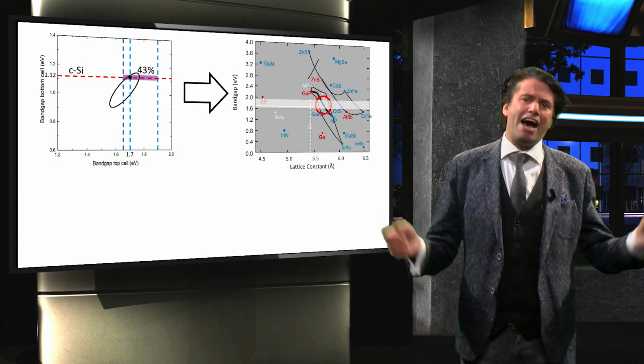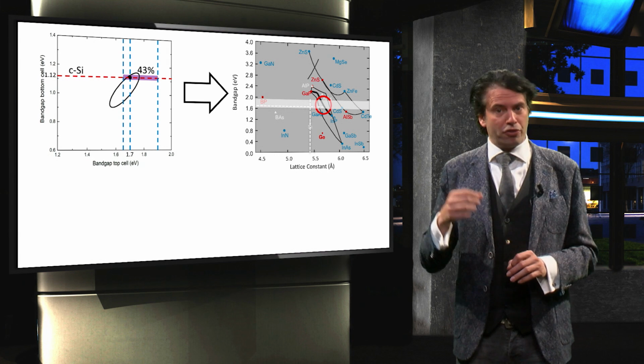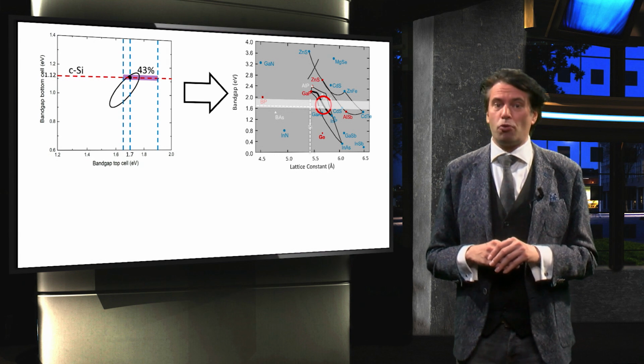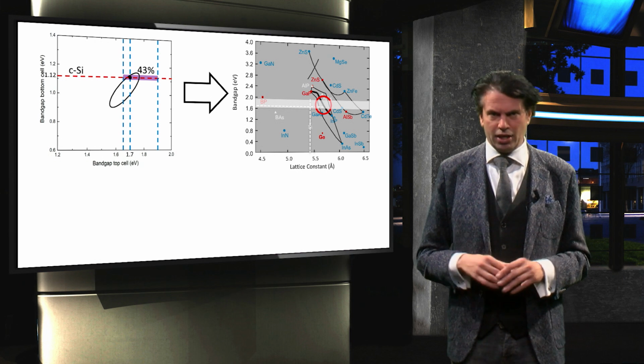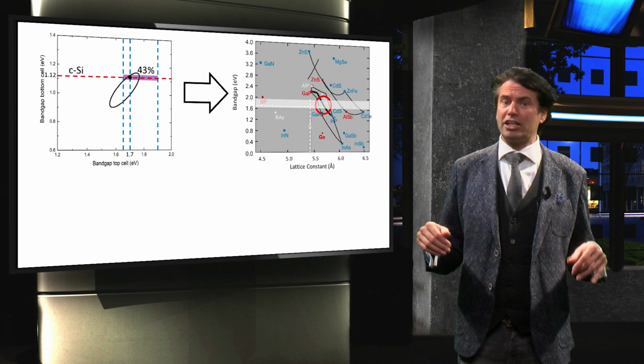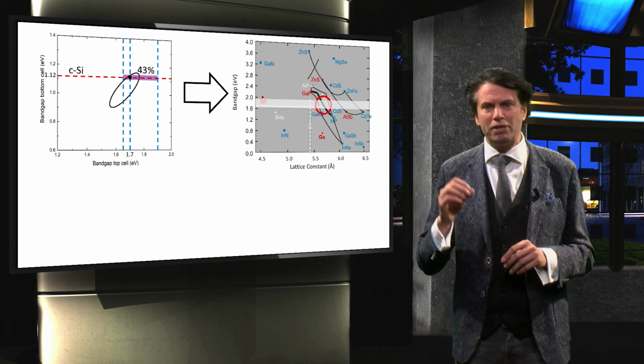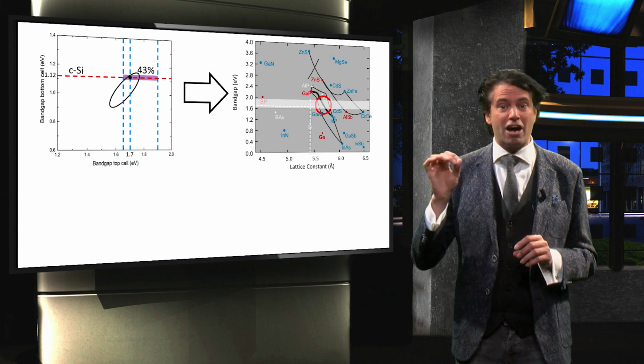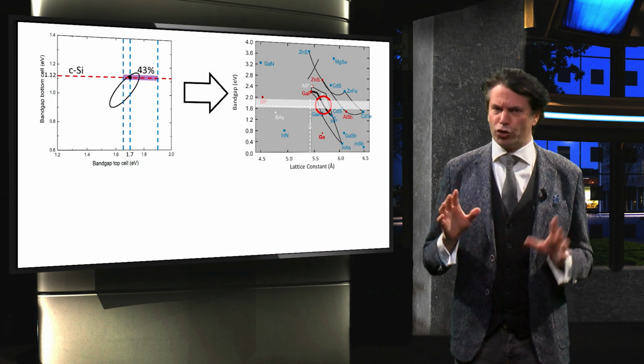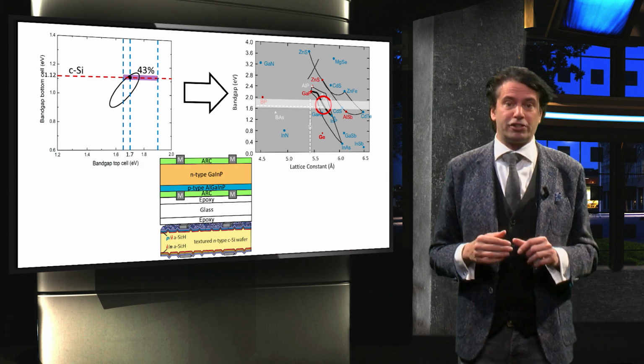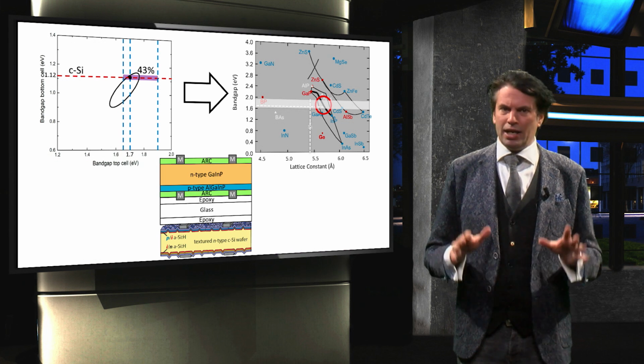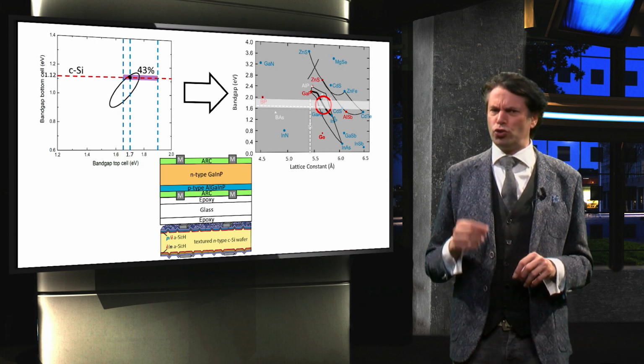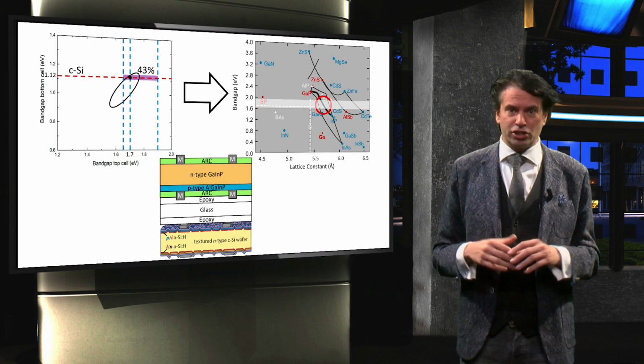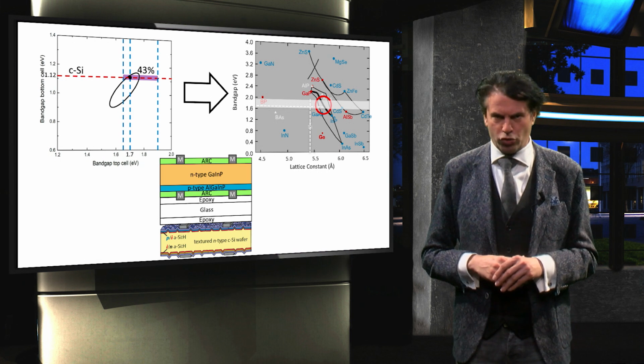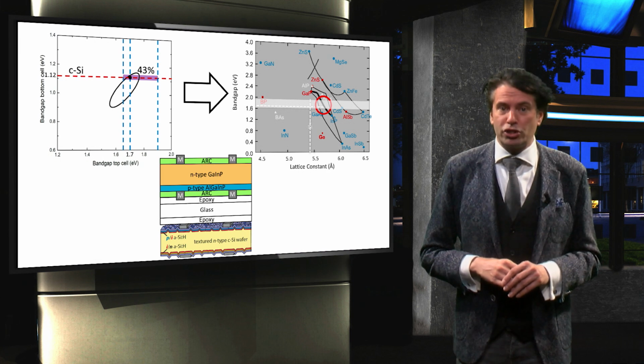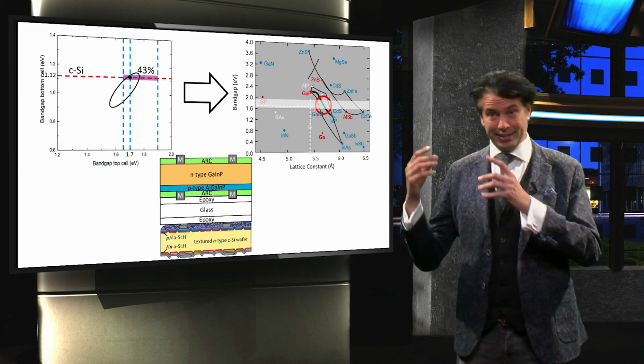In summary, we have applied the knowledge of the optimal top cell band gap on the III-V materials. We have discussed the motivation for combining III-V semiconductor materials with crystalline silicon. Since the III-V technology is relatively mature, the maximum crystalline silicon and III-V tandem efficiency should be able to reach efficiency as high as 35% based on the current technology. The 4-terminal device strategy results in the highest demonstrated efficiencies of up to 32.8%. These efficiencies are much higher than the ones achieved for the 2-terminal devices, since these face challenges regarding lattice mismatch and difference in thermal expansion coefficient. In the following video, we will discuss another hybrid device combining organic PV with thin film silicon.